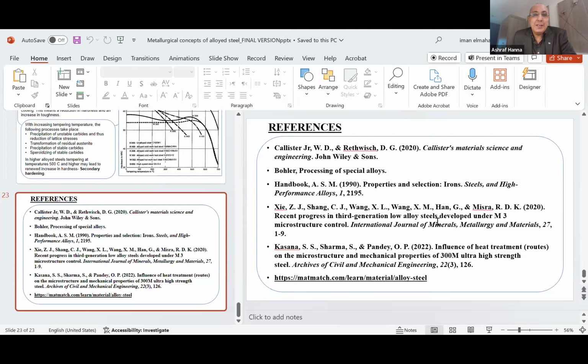From Harun El Fassi, he asked a question about whether it is possible to produce high strength steel and stainless steel without a vacuum degasser. No, actually, unfortunately not, unless you just melt it. If you just use the same raw material and you melt it in an induction furnace, just like the foundry, this is possible, but you cannot make a recipe and produce your own product by mixing a charge and obtaining it without a degassing process.